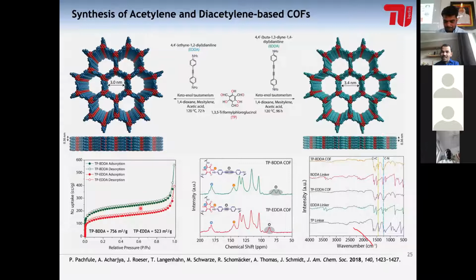So from this analysis, we could say that the COF, BDDA COF having diacetylene moieties, has the surface area of 756 meters square per gram, and TP-EDDA has the surface area of 523 meters square per gram, as expected because it has smaller pore size. Not only that, but I'm just introducing you to different methods to characterize different materials as well. For example, in this case, we have determined the surface area using adsorption analysis.